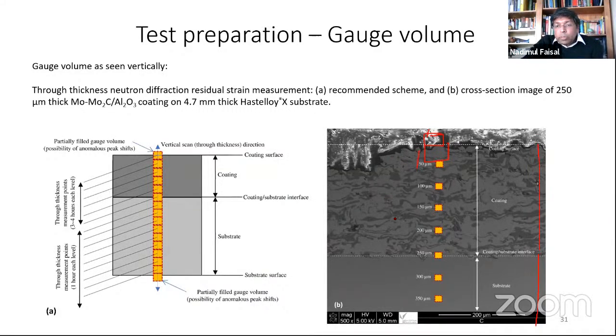And you remember, these coatings are very thin. So 200 micron, 300 micron, these are typical thicknesses. So there are only a number of points you can analyze. If you are too close to the top surface, typically I would say go to 50 micron deep, and then, depending on whether it is thick enough, you can have 4 or 5 data points from the coating, and then again you can do the same from the substrate.